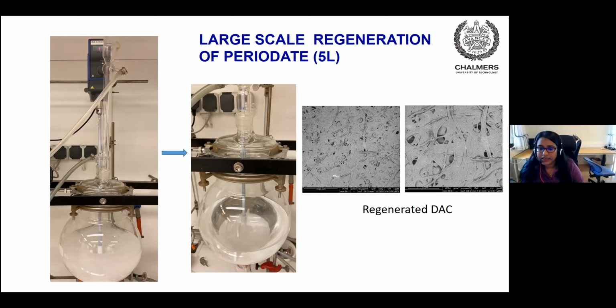You also see a picture of the dialdehyde cellulose produced from the regenerated periodate, and it is quite similar to that produced from the fresh periodate solution. So we can conclude that it can be used quite efficiently to scale up the process and to produce dialdehyde cellulose from regenerated periodate.